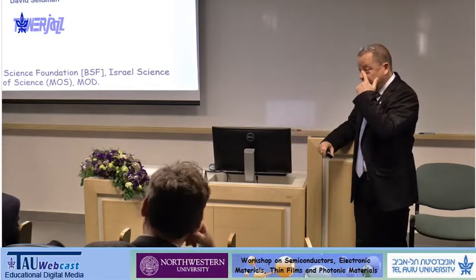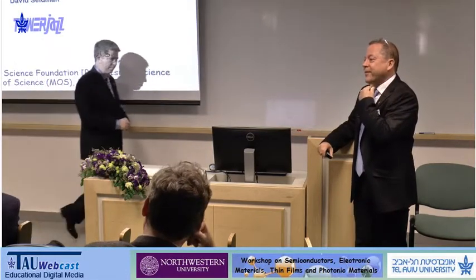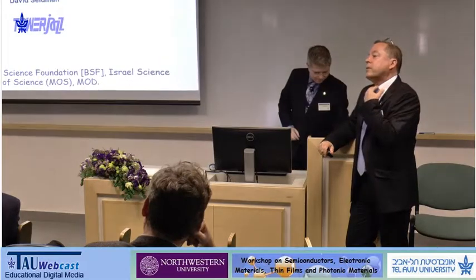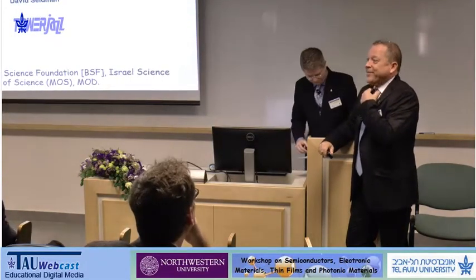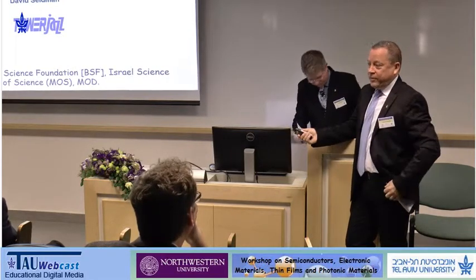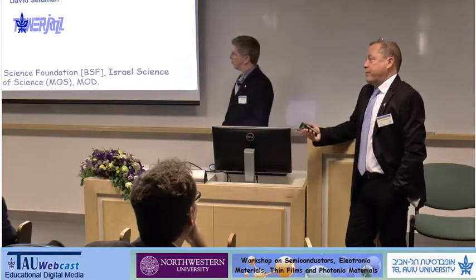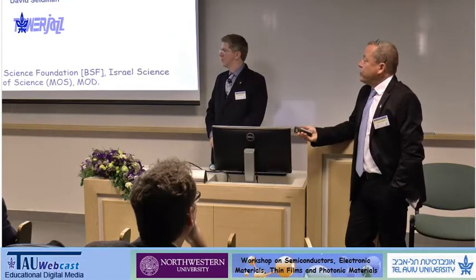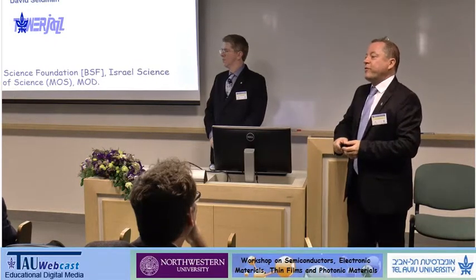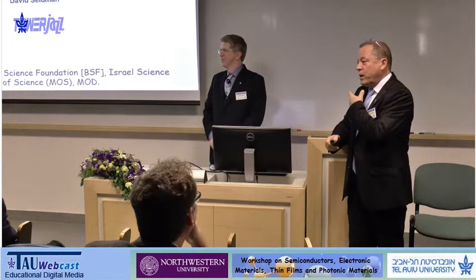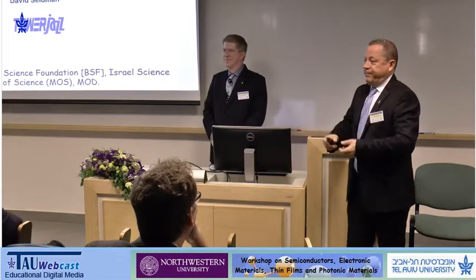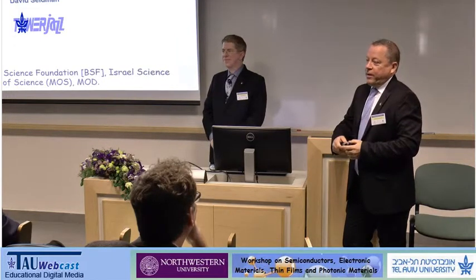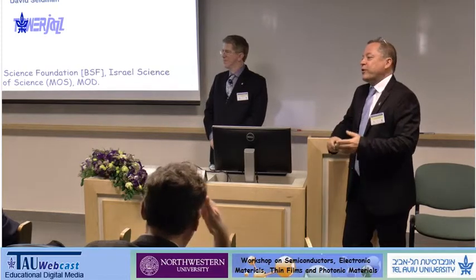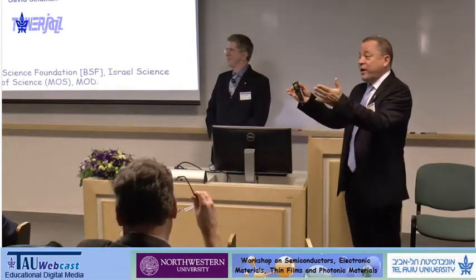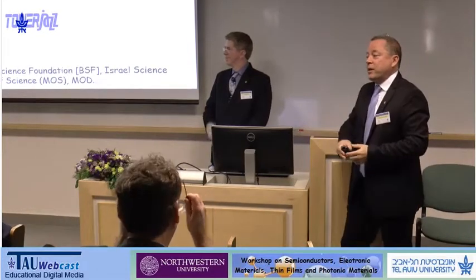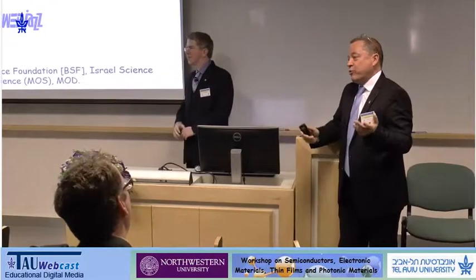SOI for the nanowires? Yeah, SOI wafers. We have not tried it. I don't know if people have done it, but they might be more sensitive. An important difference is that with the FinFET, the production is very, very expensive. The production of these nanowires is done in a very cheap fab, not a 22 nanometer node technology, but 400, because you make the channel very large and you just reduce it electrostatically. The FinFETs might be more sensitive.